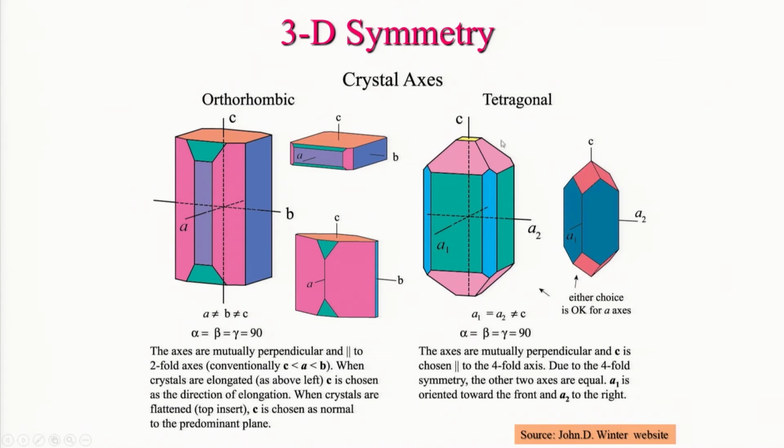And the same thing, you have a tetragonal crystal system here. In this case, this is your vertical C fourfold axis of symmetry, and you have A1 here and A2 here, and A1 and A2 are perpendicular to this crystal face shown as the green colored face here. They are equivalent faces, because C coincides with a tetrad axis, which is a fourfold axis of symmetry, and that is why a 90-degree rotation will make this face coincide with this. This will be an equivalent face, and also the crystallographic axes A1 and A2 are equivalent.